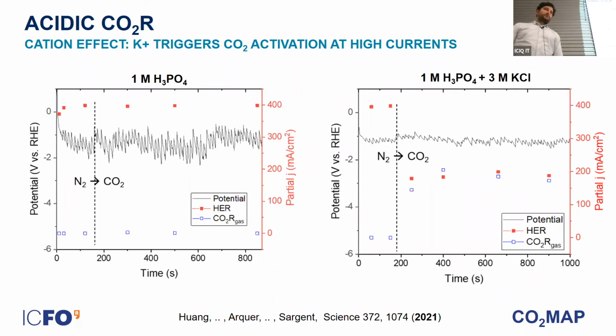Do you know? What we suspect so far, and what we actually see, and we learned a lot during this scale-up of the technology, is that in neutral and alkaline systems, one of the main reasons for loss of performance is the local formation of salts. So you start getting a lot of carbonates on top of the catalyst surface, thereby reducing the surface of the catalyst and also increasing the distance to the membrane, and this starts being complicated. At some point, you might also have some leaching of copper in case it was not under reducing conditions. So if copper is not under negative conditions, it just oxidizes, gets dissolved and is lost.